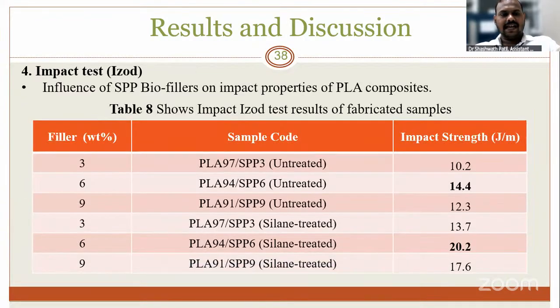As for why the treated sample always shows more strength compared to the untreated, this filler-matrix interaction and uniform distribution has been attained for these silane treated particles. And this is the impact Izod test sample results. Here we have attained 10.2 strength for 3% untreated, whereas for 6% we have attained 14.4, and the maximum we have attained is 20.2 for the 6% treated sample. These are the bar graph results.